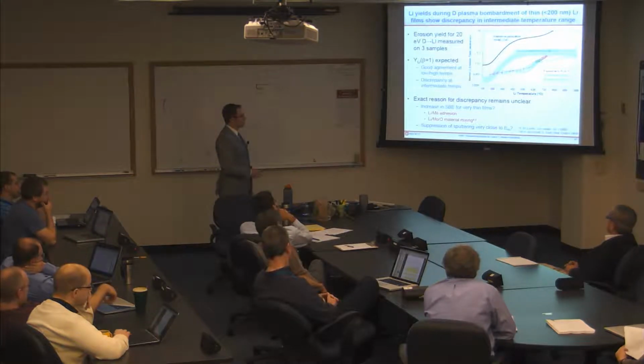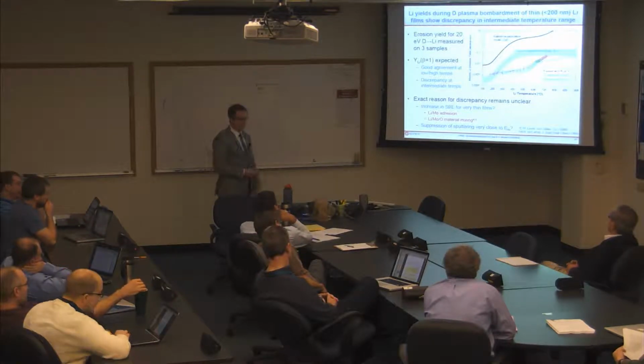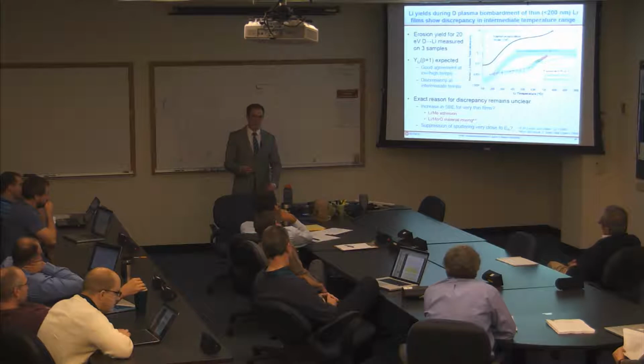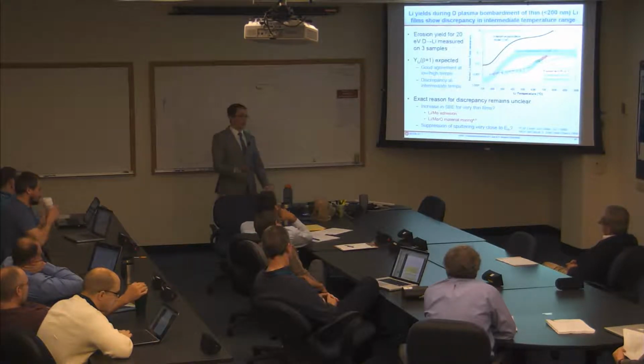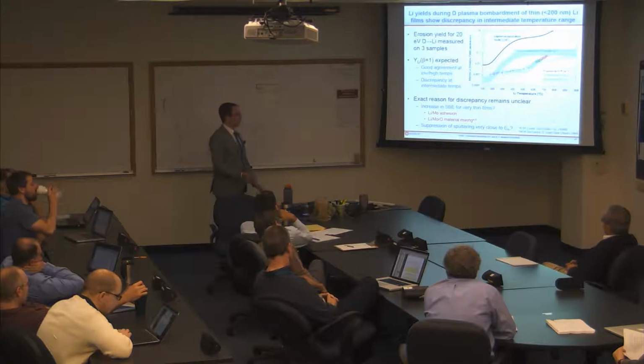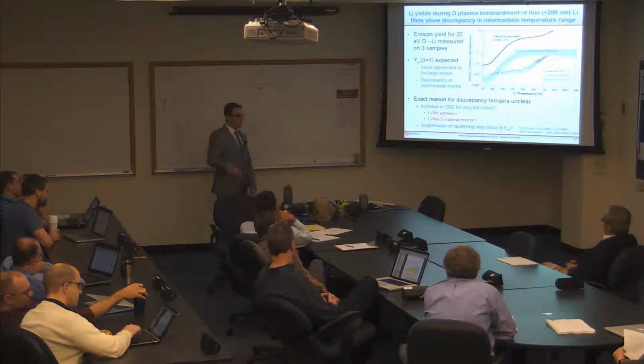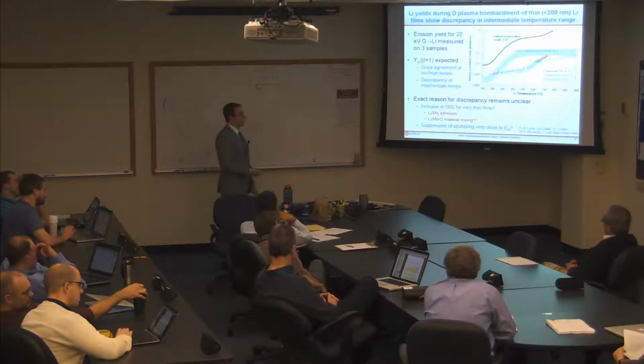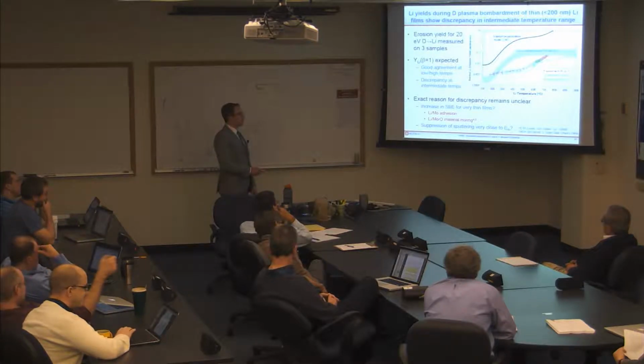This is the lithium temperature versus the erosion yield for 3 samples that were initially 200 nanometers in thickness, but because they were so thin, they actually tended to deplete in about 2 seconds. So we were only able to get data for about 2 seconds of plasma discharge. But that's okay because the temperature ramp actually mostly happens in the first 2 to 3 seconds of the plasma exposure anyway. So the predictions of the atom evaporation model are shown here in blue.